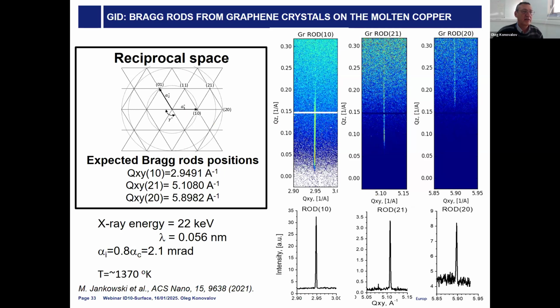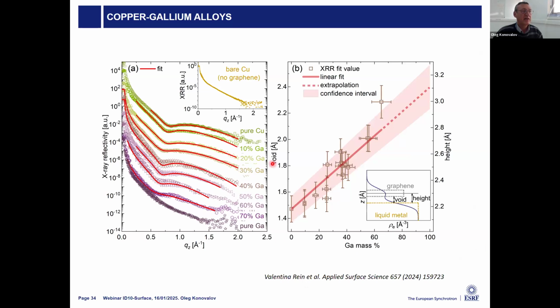And here you can see that we see up to 3 diffraction rods from liquid metal and this high temperature graphene. And then if we change, for example, the substrate, and not pure copper, but copper diluted with gallium at a different proportion, we see that this minimum, which corresponds to the thickness or the gap of the layer above the liquid metal, changes.